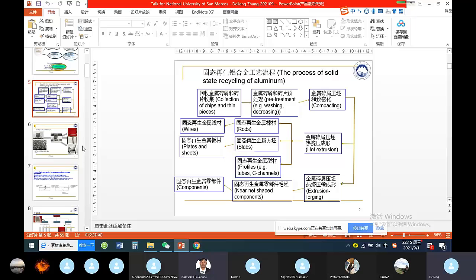Oh yeah. Of course, with primary metals, we also need to do hot extrusion. So the process is still the same. It does not really do more than for primary metal. But with the primary metal, we only do a recrystallization to get shapes. With this secondary material, like the chips, hot extrusion not only gives us a recrystallized structure, but also gives us the consolidation, the bonding between the chips. Yeah, the actual mechanical forming. Sorry, I have not done any calculation here, but from the literature, and of course we can do the calculation if you want, the amount of energy consumed by mechanical deformation is much less than melting.